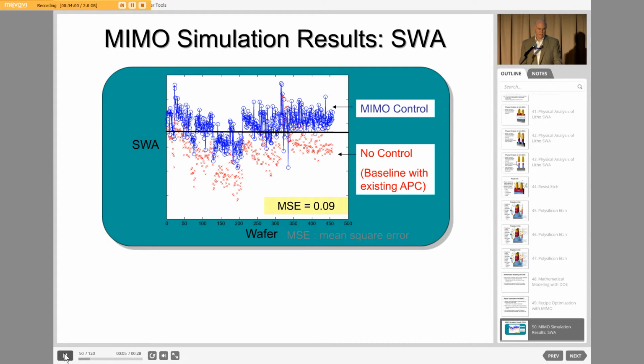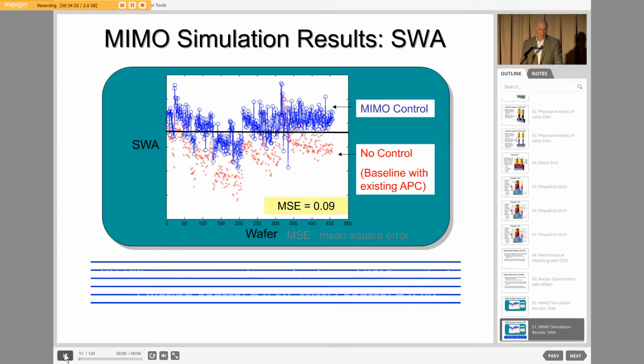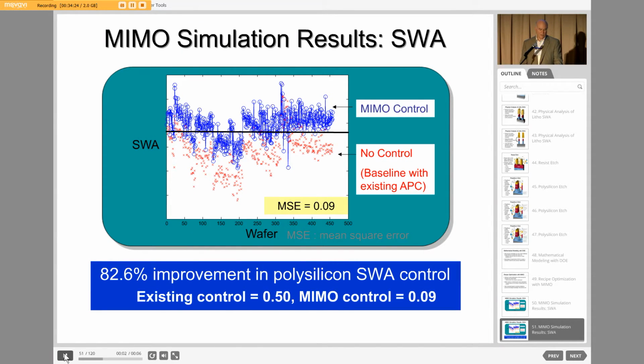So here you just see some of the results that one gets, which we did as part of the study. You can see the blue dots there are what we achieve for a consistent sidewall angle. The red X's are the ones where we said, let's just control for CD and just see where the sidewall angle ends up. And you can see that the performance is not nearly as good for the red X's that you see in the plot. So percent improvement, about 80%. That was really, I think, a great result.